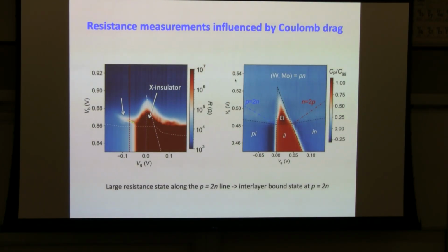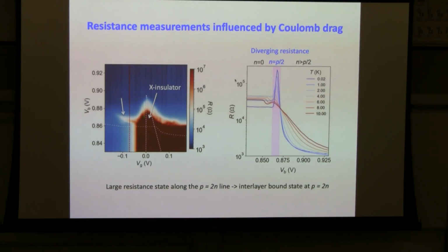What's surprising is actually that there is this feature here, which is along the P equal to 2n line, that there is a very large resistance state also along this region. And you can make a line cut along this red dashed line, and you can see that on both sides, they behave like metal, meaning that the resistance just drops with decreasing temperature. Only at this line, the n equal to P over 2 or P equal to 2n line, where the hole density is twice the electron density, only here is the resistance diverging with decreasing temperature.